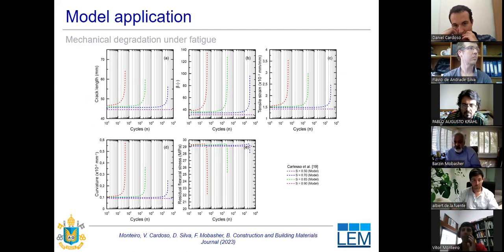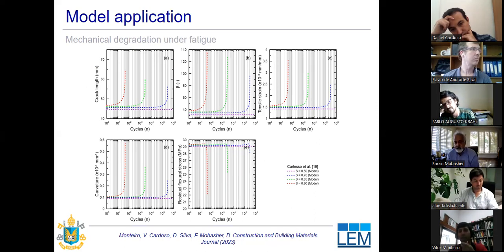So after we have the SN curve, the CMOD evolution, and the closed form solutions, we can study now how the other mechanical parameters evolve under fatigue loading. So we can verify the evolution of the crack length, which is a fracture parameter, how the crack length is evolving in fatigue, how the tensile strains are evolving under fatigue, the residual flexural stress, and any other parameter that we want that is calculated through the closed form solution. So after this parameterization, we can go from CMOD evolution and calculate the rest of the parameters.